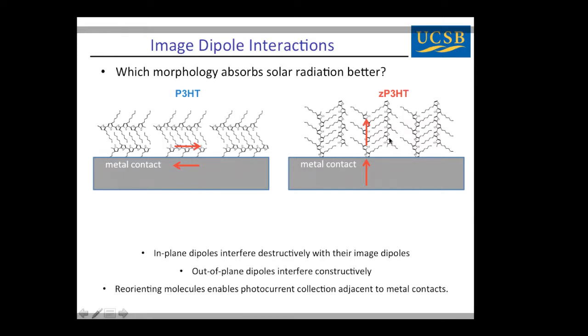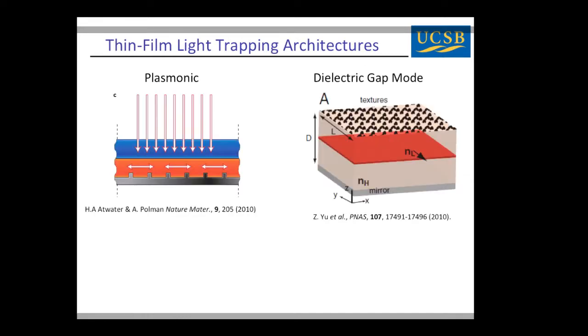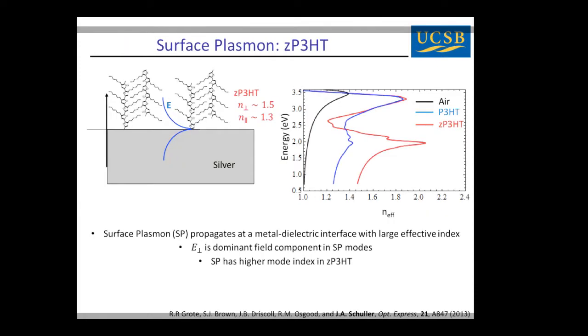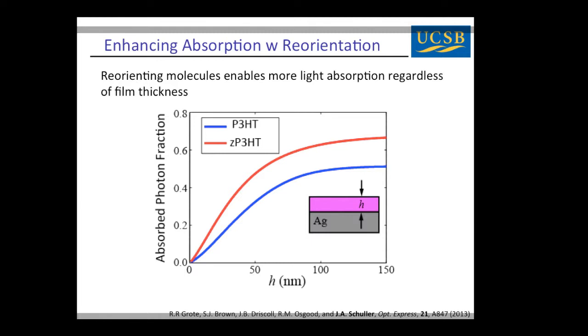Okay? So bad, good. So that was the reason we thought that this hypothetical morphology might be better. Okay? And so what we did is we looked at two different light trapping architectures, one based on metals or a plasmonic mode, and then also one based on high index dielectrics. So now it doesn't rely on this quenching effect of the metals. Okay. And since we're coming on 50 minutes, I'll just wrap up without going through the details. We can look at the surface plasmon calculations. And these are very, I believe, conservative calculations or estimates of the optical properties of this vertically oriented polymer.